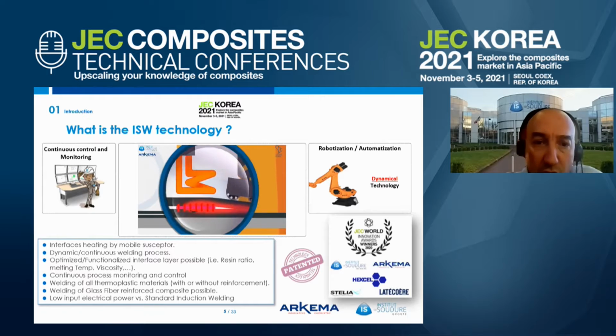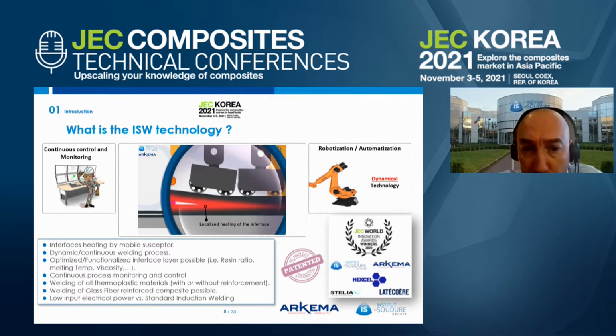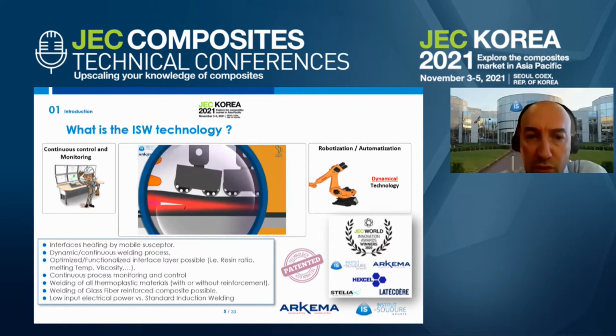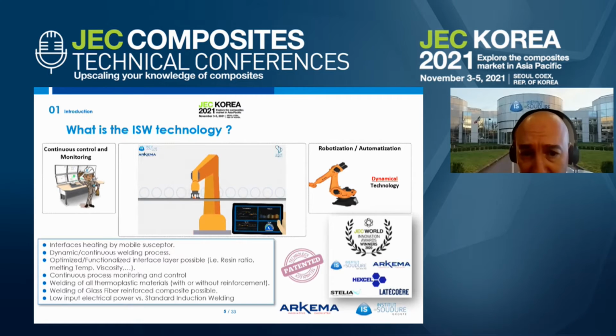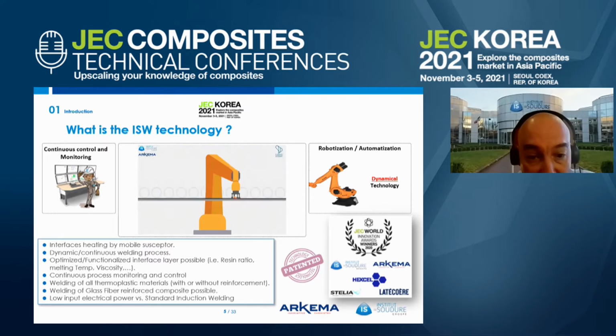So we are using a mobile coil that is linked to a mobile susceptor that is located between the two elements that we want to weld. And we will concentrate the energy, meaning the heat, at the interface. So we are not fully heating the components, and we are not decompacting also. So we localize the energy that allows us to have different kinds of characteristics, and that allows us to weld with LSP and so on, something that I will share with you just after. So this is a fully dynamic and automated technology. We have been awarded in 2020 with the JEC Innovation Award in JEC Paris, and with our partners that followed us from the beginning with the development. Arkema, of course, this is a partner of the development, but also Hexcel, Stelia, and Latecoère.